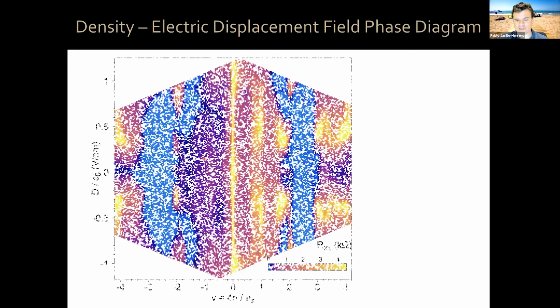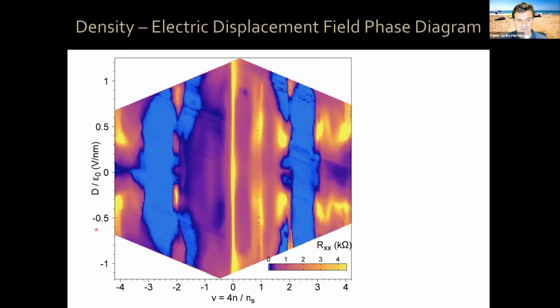So we have this independent density or filling factor and displacement field. So this is what the resistivity versus filling factor and displacement field looks like. It's a very complex phase diagram. Let me guide you. Superconductivity occurs in these light blue regions. Those are the superconducting regions. And resistive features are in yellow. These are highly resistive features.